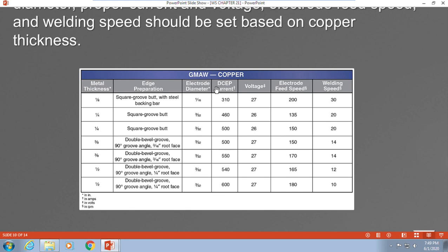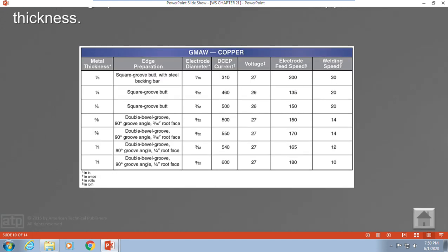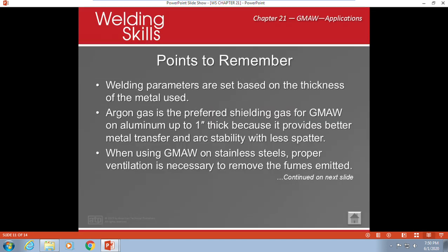Now, quite honestly, I'm not even sure if the machines that we have get this hot. This means this thing has to be flying, and we have to put a bunch of heat into this. Look at this. Our welding speeds 30, 20, and 20. And if we look at the little note, it says in inches per minute. I have to do 30 inches per minute in order to get this into this 1/8 inch. That's a ton of heat that has to go into this. Now, remember, welding parameters are set based on the thickness of material.